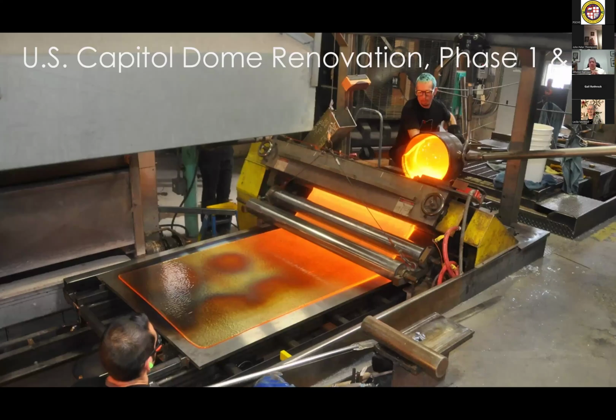And then we worked with a company in Oregon to cast new sheets of glass. They do all kinds of fancy high-end glass, but they created a custom steel platen, which is the table that it's coming out on. And that was preheated to 500 degrees. And then the molten glass was heated in a big kiln and chemically made to be as close to the original glass as possible. And they would take giant ladles, and then, of course, carefully, because it's 2,000 degrees, bring that ladle of glass over as fast as possible, pour it into this machine, which is like a big pasta roller. And then where that 2,000-degree glass hit the 500-degree temperature, it developed a series of chill marks. And you can just see those in the glass surface. And those are very similar to the chill marks that we had in the historic glass.